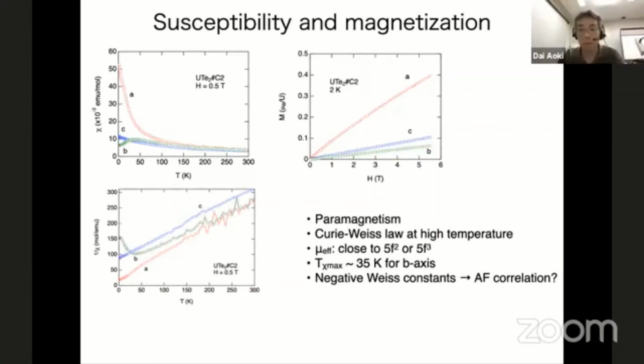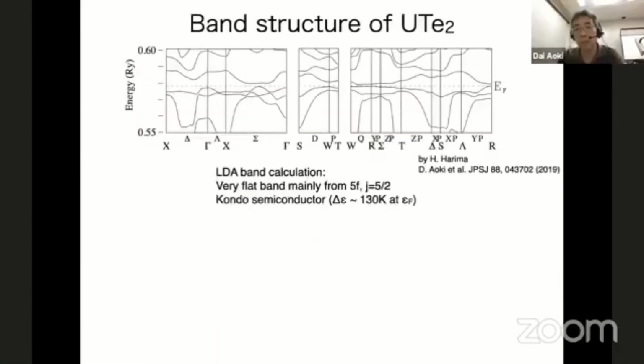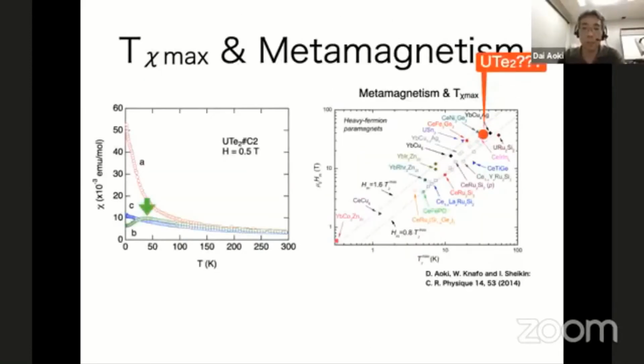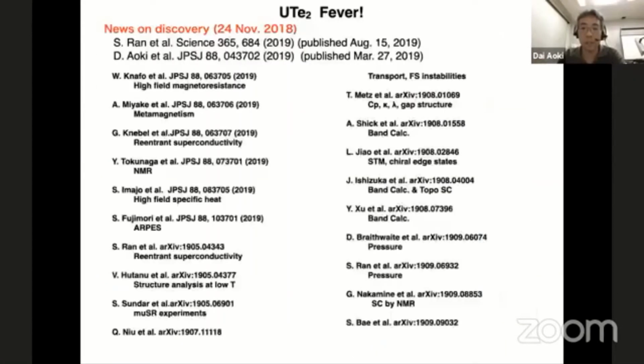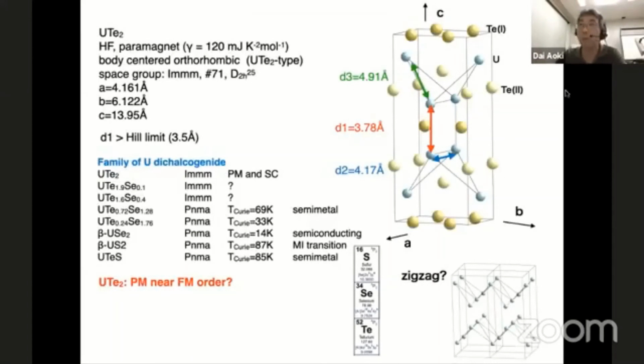The reason why it doesn't show magnetic order is theoretically explained. I think it's a paper by Xu. The crystal structure is somehow special, and they discuss that some frustration occurs in this material. Because of the frustration, they propose that magnetic order does not occur, but both ferromagnetic fluctuations and antiferromagnetic fluctuations exist. This is the theoretical view.